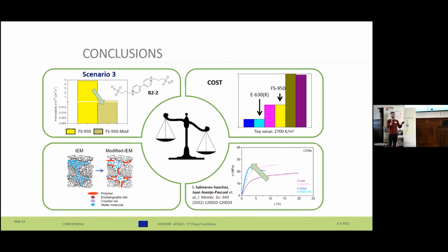we have made some tensile strength analysis, and we observed that our modification enhances the mechanical strength as well as the flexibility of our membrane, which is something interesting from the stack manufacturing point of view, because we are extending the lifetime of our membrane material. And this is something we have recently published, as you can see.